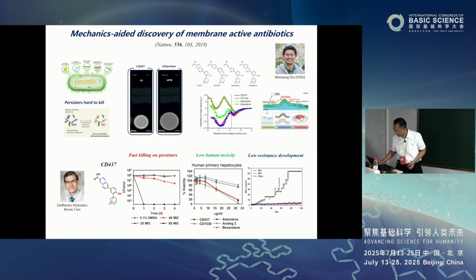So here are some simulations, and here are some experiments. Underneath are experiments, and these are simulations. You can see that, for example, this case corresponds to the blue curve, CD437. It was able to invade into the membrane and cause this kind of rupture. You see the aggregation in the membrane, and it causes perforation in the membrane.